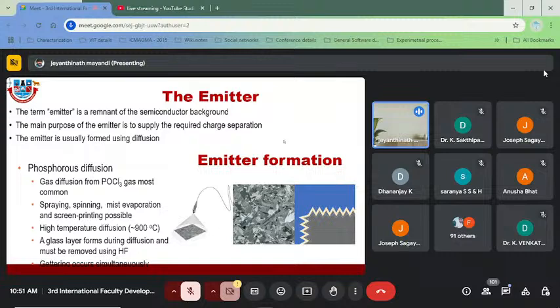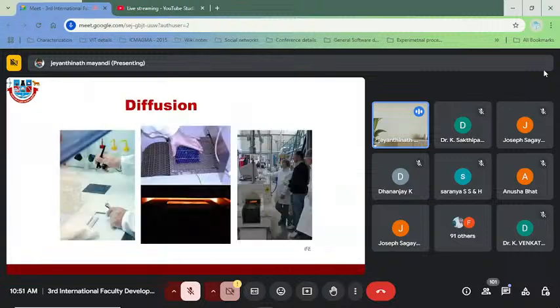And this also getters. What gettering means is that the impurities present in the bulk material are also sucked up into the n-type layer. So gettering happens simultaneously, and the n layer will have all the impurities from the bulk. This is one method of getting the phosphorus into the wafer.